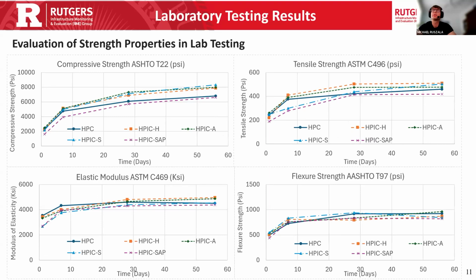So going on to the strength properties, we have all the mixes that we tested, the lab mixes. We saw that HPIC did better in all cases. A little bit different variance with the flexure strength, but with compressive strength, tensile strength, and elastic modulus, we saw that HPIC did as good or better. And in all cases, we saw the SAP did just a little bit worse than the control mix.